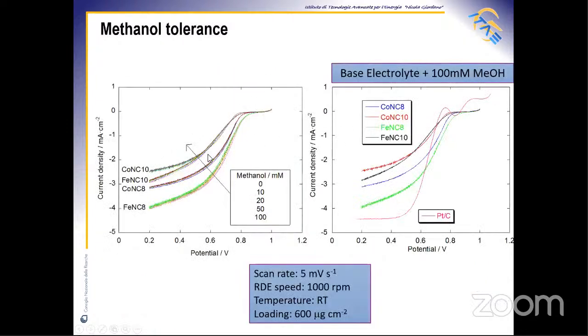These figures show the oxygen reduction reaction curves obtained in oxygen saturated perchloric acid without methanol and with four different methanol concentrations. Thus, each catalyst is characterized by five curves. These results highlight the excellent methanol tolerance of such compounds, pointing out the promising characteristics in order to be used in direct methanol fuel cells.